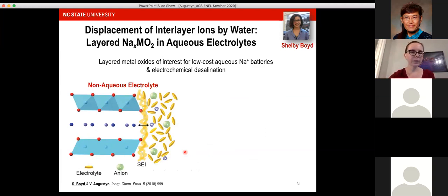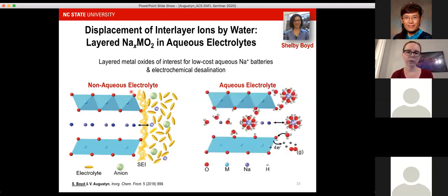In the case of non-aqueous electrolytes, you almost always assume that your cation is moving into the material in a desolvated state, that you may have to pass through a solid electrolyte interface layer, but the desolvation energies are lower in non-aqueous electrolytes. On the other hand, in aqueous electrolytes, you don't have the SEI formation. The hydration energies are much higher, especially for ions like lithium or sodium. And so now you have to consider the solvent, water, as taking part in the intercalation process.